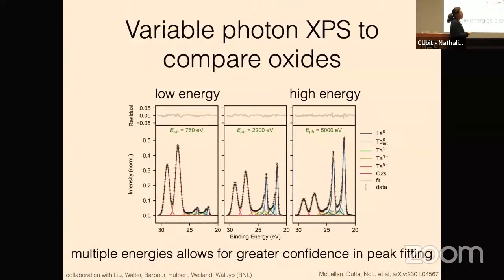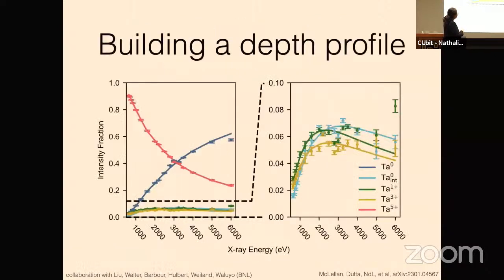So if we know that the same peaks have to appear at every single energy, and we take 50 different energies, now I have a very highly constrained search. So maybe for the first time ever, I am pretty confident at the number of peaks in this mess down here. So then we can use that to build up a depth profile of all of these different species.